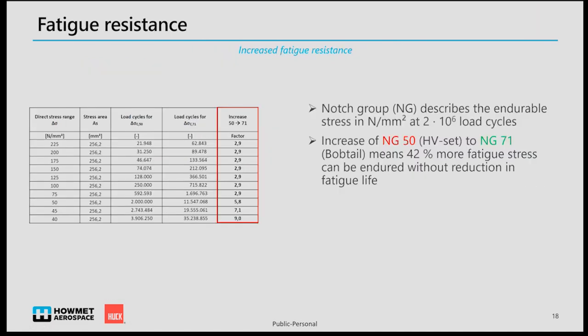Here on this table, this is again highlighted depending on the actual stress in your joint or on your fastener. This can increase the fatigue life up to a factor of 9, depending on the amount of stress you have, and with the changing slope of the fatigue curve, the fatigue resistance even increases in direct comparison to the threaded fastener.